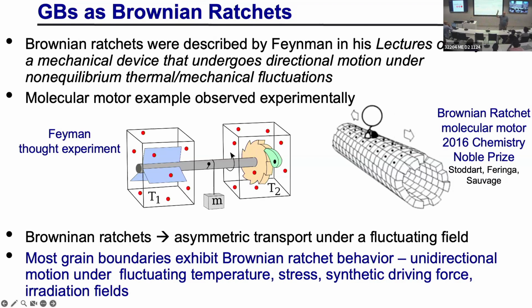Now, I can show you lots of examples of grain boundaries. If I take an interface between two phases, those are almost always asymmetric. If I take a dislocation in a non-centrosymmetric crystal and look at the core structure, its motion this way and that way will be different. A classic example is screw dislocation motion in cubic materials. So by putting on a stress, I should be able to do this experiment.